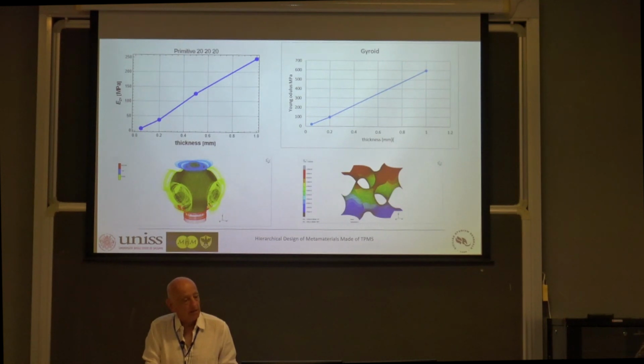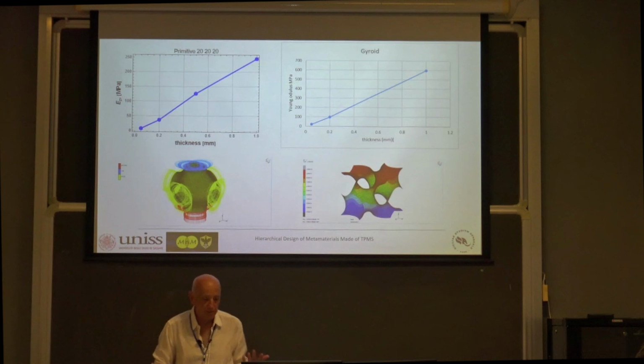In this case, this is the Young modulus. By the way, both the primitive and the gyroid, which are the surfaces I will talk about, behave in a cubic way, so they're isotropic. This is the Young modulus as a function of thickness. It is interesting to see that there is a linear variation: increasing thickness, stiffness increases linearly. That means that, as we expected, the deformation behavior is membrane dominated. Otherwise, we should have found a cubic dependency on thickness. So it's very interesting.